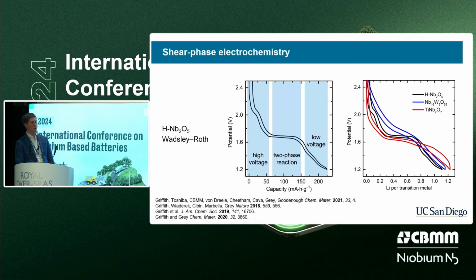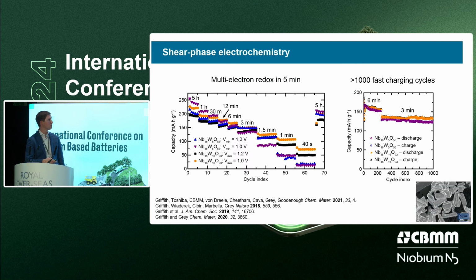At the very least, we should be interrupting strain and interrupting the ability of lithium cations to order. That makes sense, because if you have these high valent cations that are disordered through the structure, then lithium isn't going to be able to find low energy ordered arrangements within those disordered high valent cations.